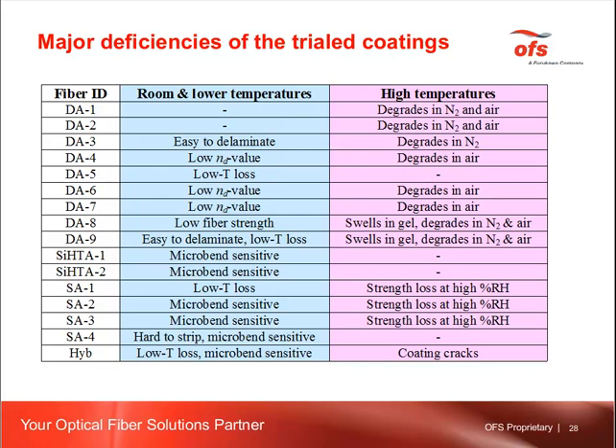And once again, most of the coatings are commercially available. So we placed deficiencies only in this table. The blue column corresponds to deficiencies observed at room and lower temperature. The purple column corresponds to deficiencies observed at higher temperatures in harsh environments. Nothing in a certain cell means that there are no or almost no deficiencies.